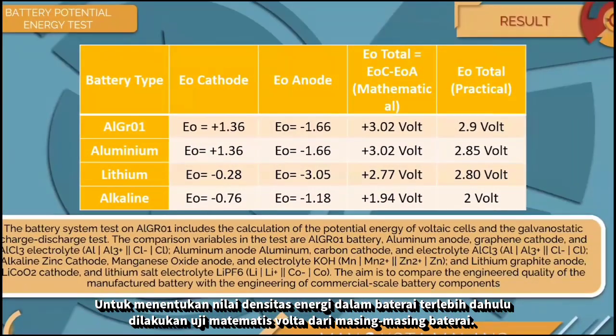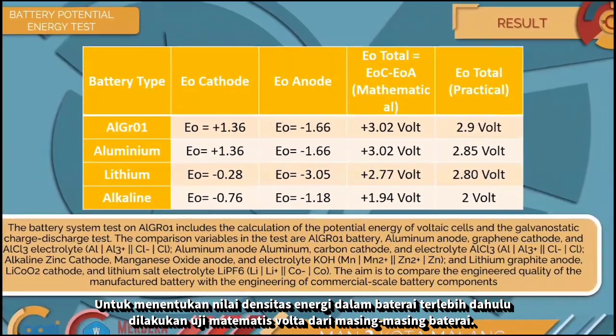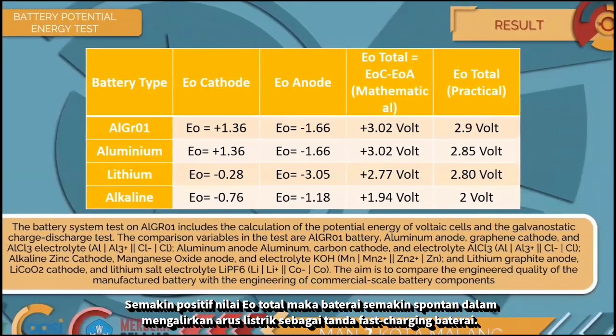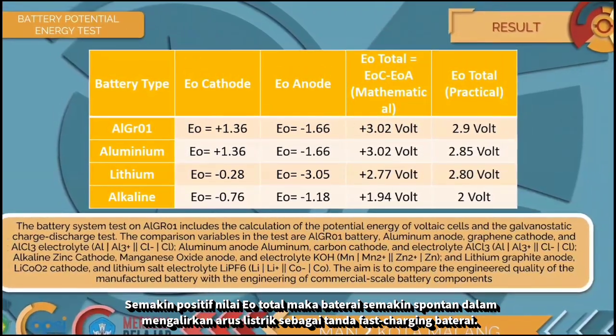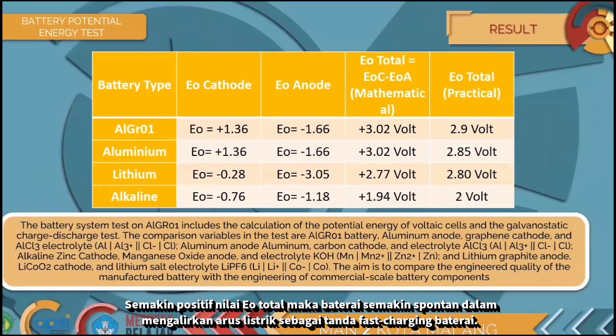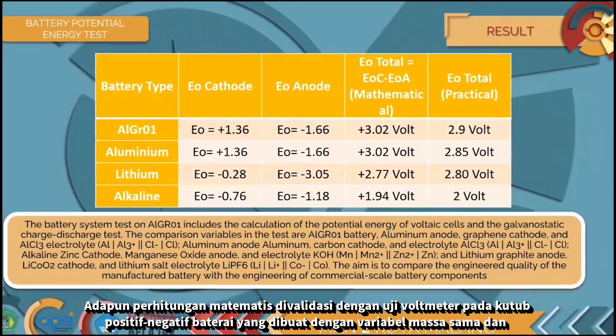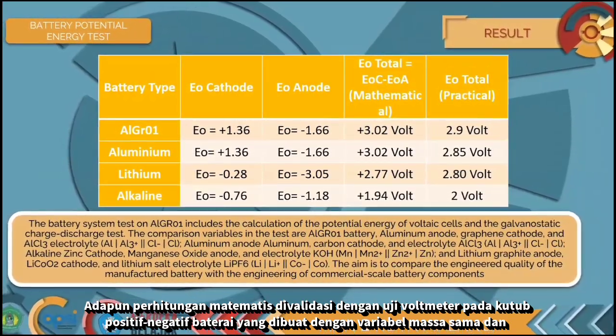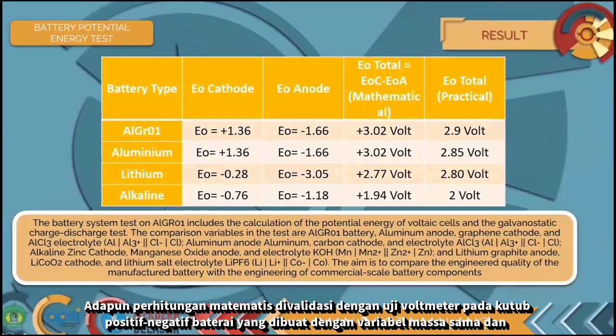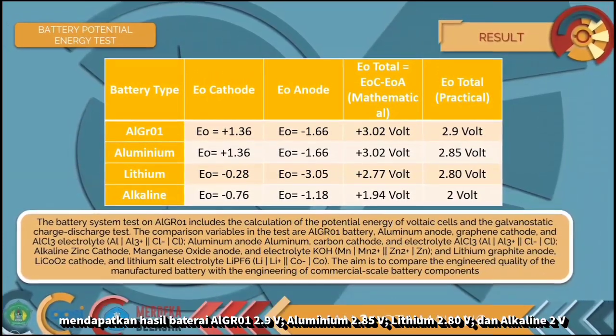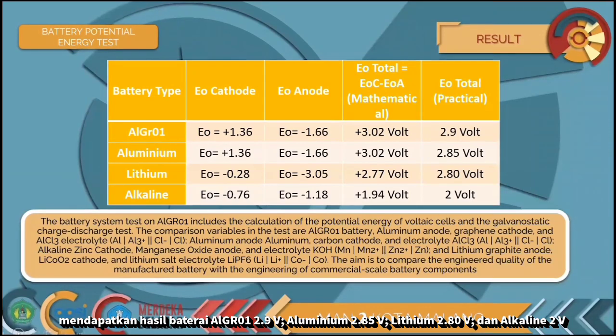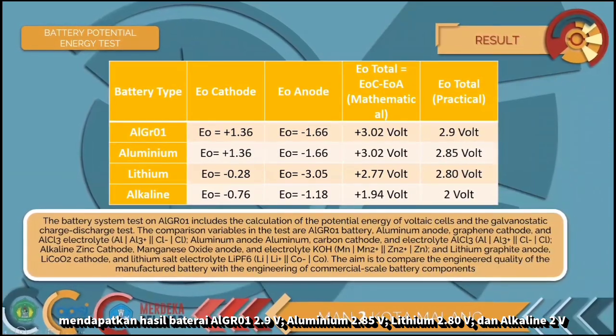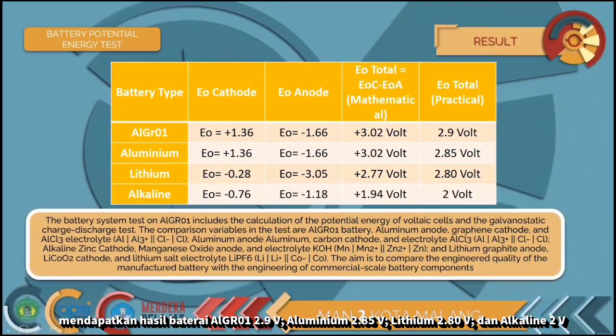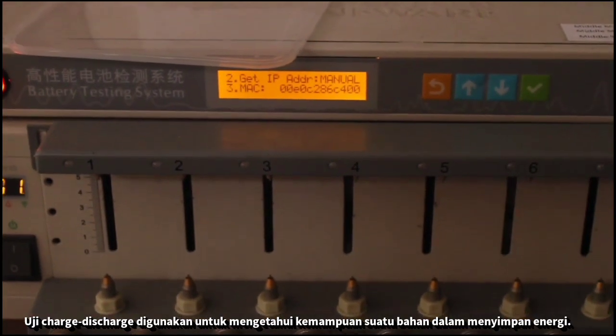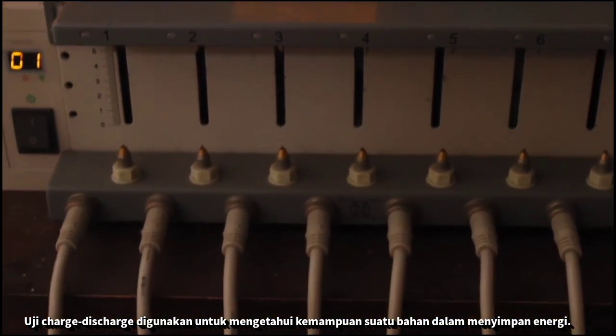solution. To determine the value of the energy density, a voltaic mathematical test is first carried out. The more positive the total E value, the more spontaneous the battery, as a sign of fast charging. The mathematical calculation will be validated by a voltmeter test on the positive and negative poles of the battery, which was made with the same mass, and obtained the results of a 2.9-volt ALGR1 battery, aluminum 2.85-volt, lithium 2.80-volt, and alkaline 2-volt. The charge-discharge test is used to determine the ability of a material to store energy.